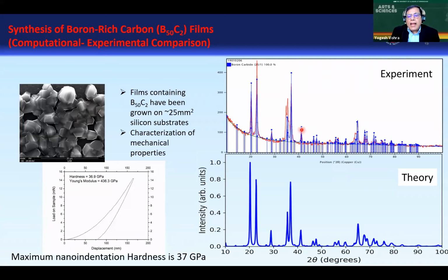And there was an excellent agreement between theory and experiment in where the X-ray diffraction peak should be, and the hardness is about 37 GPa. So this material, we suspect, will be very stable under high temperature environment and could be used in applications which require high temperatures and high strength.